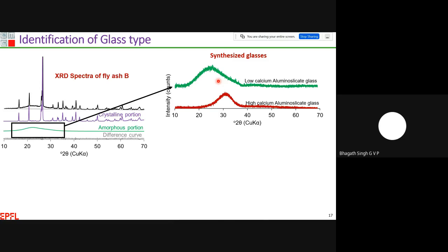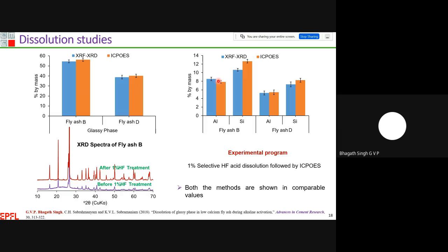Then once I had identified the glass, I carried out the dissolution studies, to see how the glass behaves in various environments. And before that, I tried to identify the total glass content present in our fly ash by using the existing methodology, that is 1% selective HF acid dissolution, by comparing with the XRD technique, which I have used throughout my research.